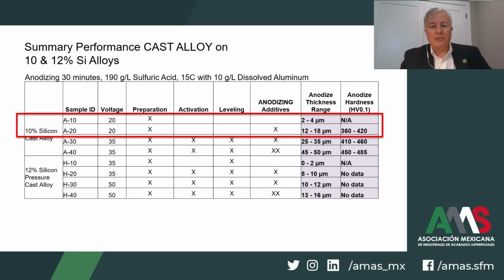In looking at even higher silicon containing alloys, in this data set shown on the slide, different cast parts were evaluated for anodizing quality after following the cast alloy approach, looking at two different casting approaches, including castings from the pressure cast and those from gravity cast. As the data shows, the impact of choices for stage 1 and stage 2 will have on the oxide thickness and the hardness. As shown in the red box for the 10% cast alloy case, including only the additive package to the anodizing solution slightly improves the ability of the oxide to form a thicker layer versus the baseline attempt without the cast alloy approach to the anodizing process.